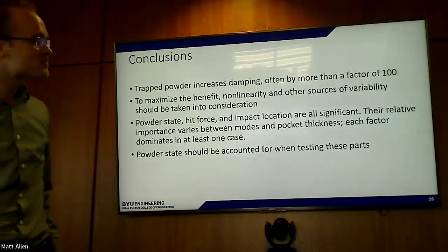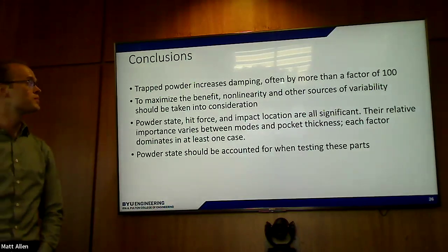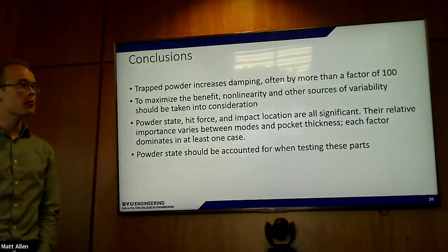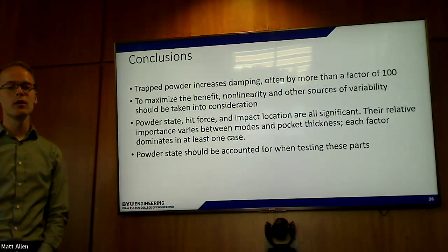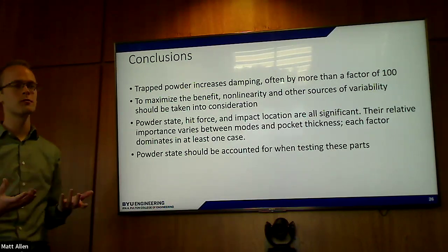So with this data set in hand, we're able to see that for some of the modes, the damping increased by more than a factor of 100 relative to this fully fused powder, or relative to the fully fused solid beam.